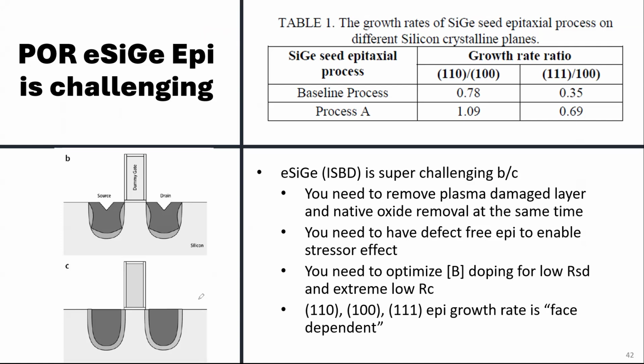And when you want to do it, first of all, you have to remove some layer. You need to remove plasma damage and native oxide. So the first layer here, you have to do some work to remove it, to clean the surface. Okay, you need a defect-free epi layer. Your seed layer has to be defect-free. So you have a nice source drain. And you want to grow it flat this way. You don't want to grow it like this. That one you don't want.